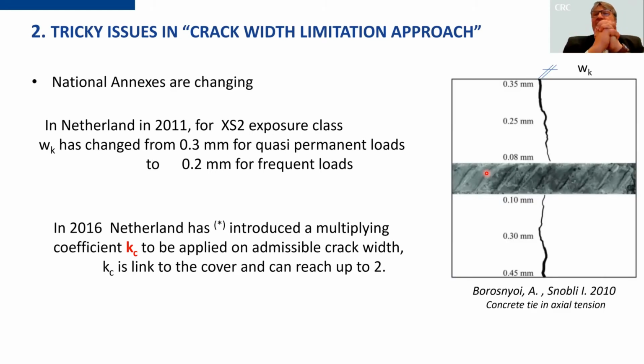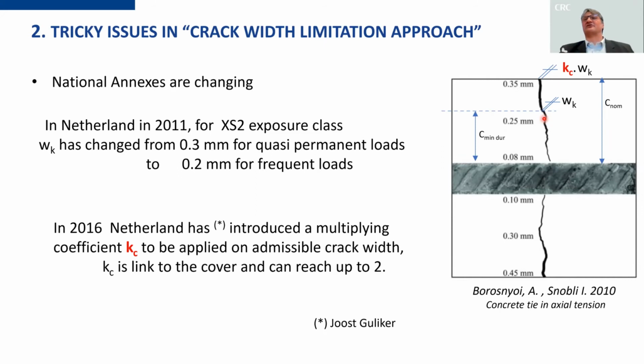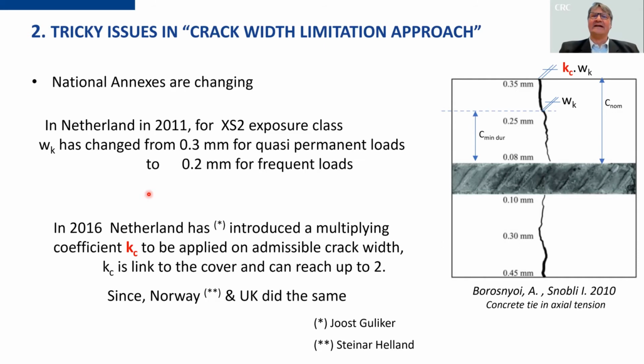The idea is the following. You have here the reinforcement and the crack, with a shape with a width which diminishes with the thickness. Here you have the nominal minimum durability cover, and what you want is to have WK at this location. So you admit for the nominal cover a higher opening. So somewhere in 2011, you increased the amount of reinforcement, and in 2016, you decreased the amount of reinforcement. Many countries, such as Norway and the UK, did the same.